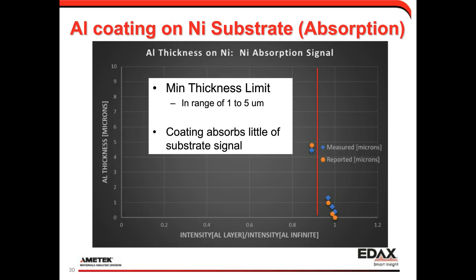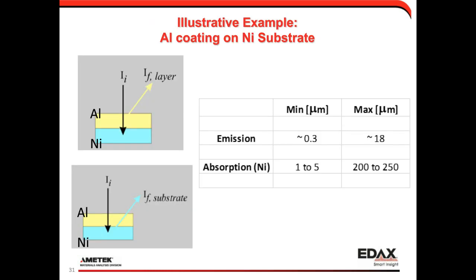I didn't carefully try to plot that all out. The idea was just to be able to make some comparisons between an emission mode and an absorption mode. So you can see in this table here where the two ranges are dramatically different. The absorption mode, you can measure a much higher thickness level. The emission mode will give you access to thinner layers.